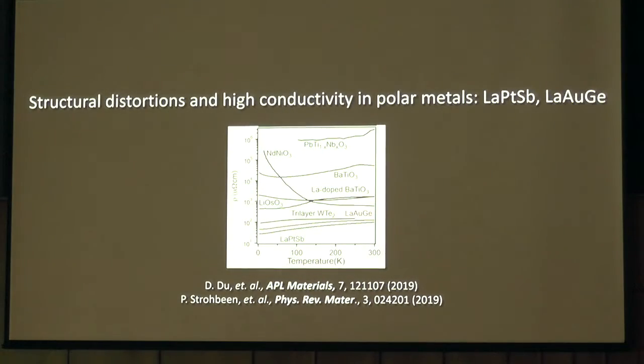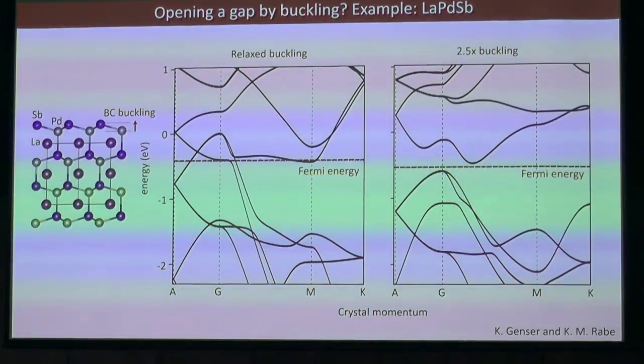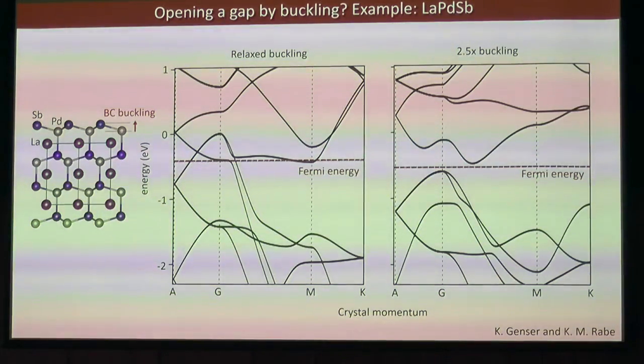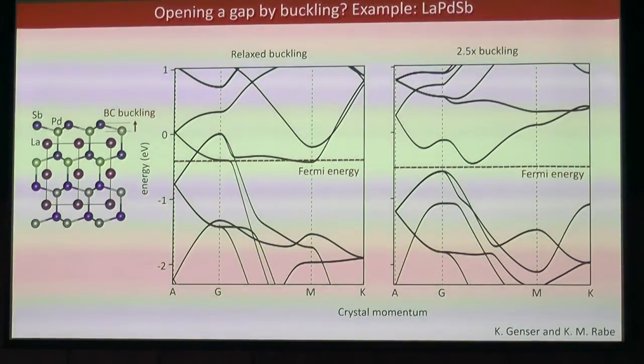Okay, second part. Now I'm going to talk about our secondary strategy, which is to take these compositions that are natively metallic and polar and ask the question if we can induce strong enough structural distortions to open up a gap. Okay. So the basic idea looks like this. Here's an example of lanthanum palladium antimony. Lanthanum is at the stuffing site. Palladium antimony makes this buckled wurtzite lattice.